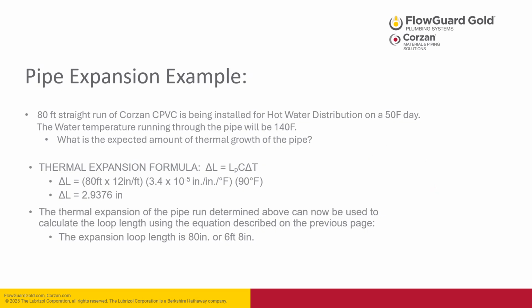Now let's look at an example. For an 80-foot straight run of Corzan CPVC that's being installed for hot water distribution on a 50-degree day, the water temperature running through the pipe will be 140 degrees Fahrenheit. What is the expected amount of thermal growth of the pipe? Well, we take the factors relative to the piping, calculate it for a 90-degree temperature change, and it results in approximately 2.9 inches of thermal growth in the pipe.